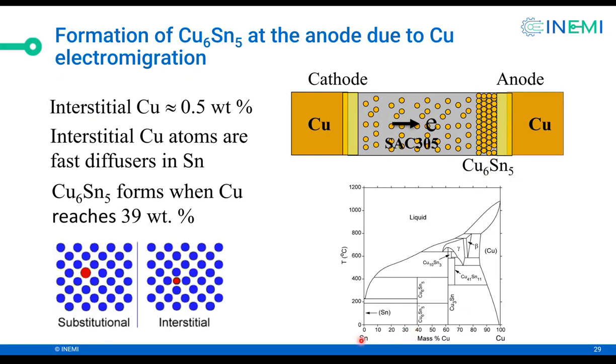If you look, this is tin, this is copper. At 39%, there's the intermetallic Cu6Sn5. So when the composition of this alloy reaches 39%, Cu6Sn5 precipitates and it grows in this direction towards the cathode. And we'll see that.